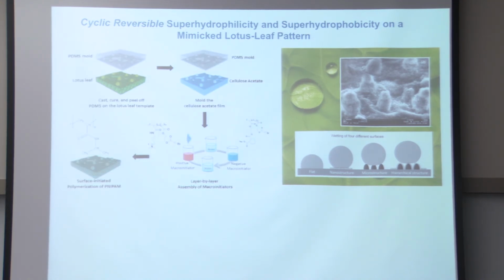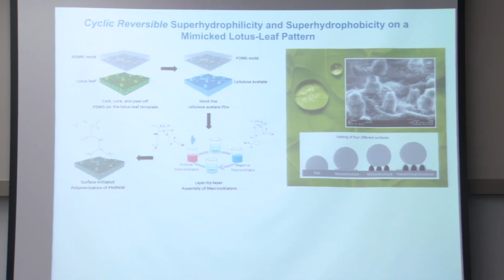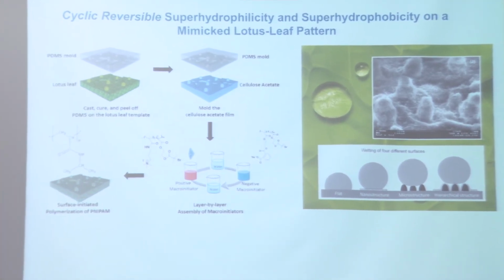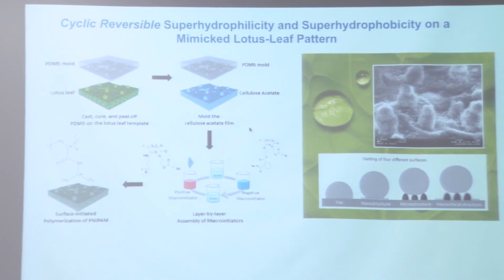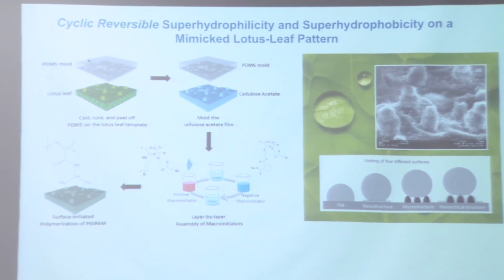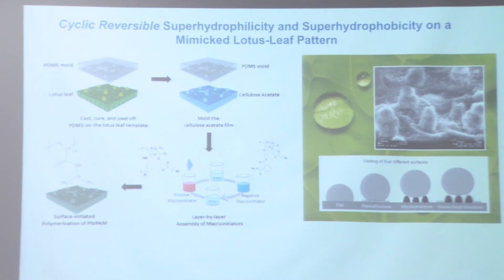Here are the steps we've taken—some of the students will be at the next lecture where I'll explain more of this. For now: we take a PDMS mold and replicate the lotus leaf. We take that PDMS mold and stamp it onto a cellulose acetate film. That cellulose acetate becomes a replica of the lotus leaf—an artificial polymer version. Then we coat it with polyelectrolytes that also act as initiators for ATRP.